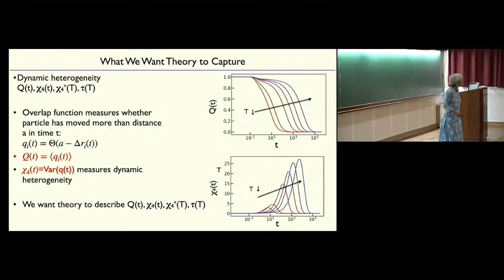Andrea, I have one question. Related to what Rajesh asked, close to this MCT energy, you see that you go through a transition, not a crossover in some sense, from barriers which have multiple unstable directions versus barriers which have one direction. The saddle index becomes 1 below a certain temperature, which seems to be very close to the MCT transition temperature. So do you see some signature of those even in the softness? No, I would say not. Again, we're only looking at the barriers that the system actually goes over.